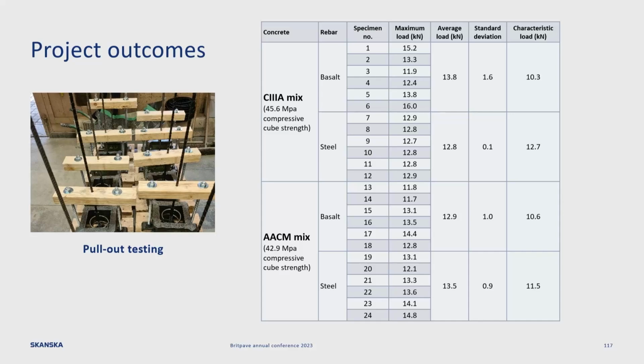Even though the final performance, the ultimate failure in the pull-out test, as you can see, was extremely comparable between steel and basalt, the graphs, if you read the report and look at the detail, give you an indication that maybe there's a little bit more slippage going on with the basalt bar with the helical winding. So a bit more further research required.